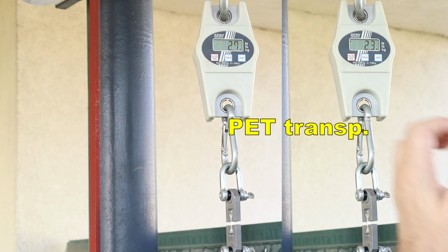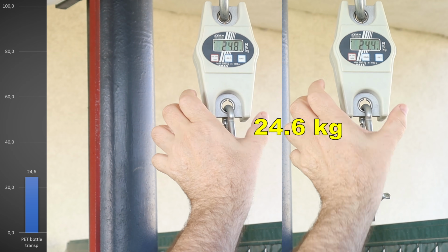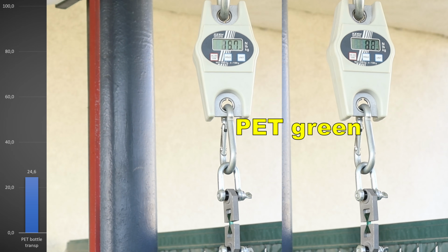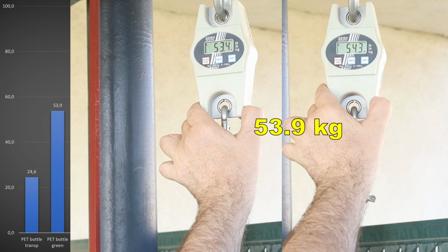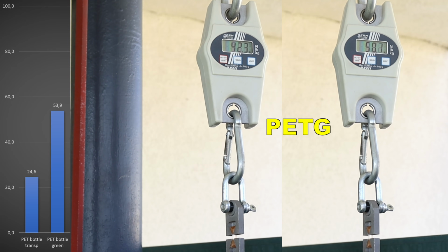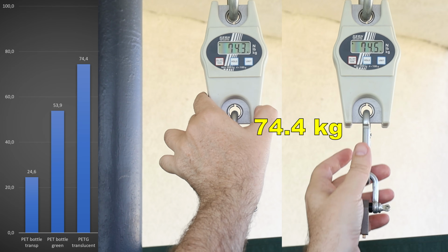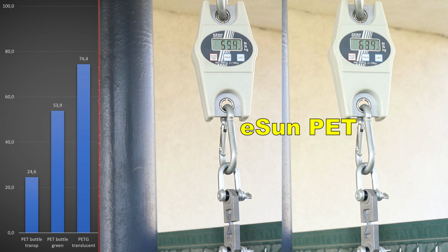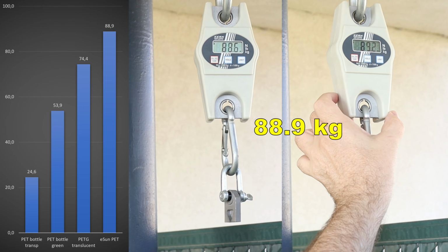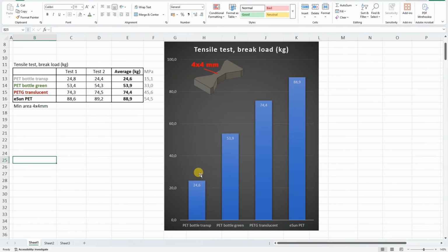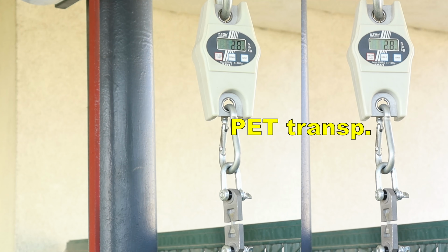Tensile test horizontal printed objects. On the left side you can follow the comparison numbers. As expected, the transparent PET is very weak, but even the green version is weak too compared to the PETG. eSun PET. This number is very similar to the measured value in the review video of this filament. This means that we can still expect some higher values for the recycled PET if the print settings and extrusion is set correctly. Layer adhesion, vertically printed specimens.